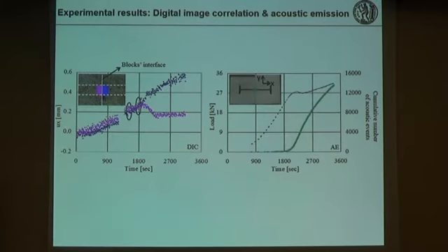And moving on to the results of the digital image correlation and the acoustic emission, on the left, in order to take advantage of the data of the DIC, what we did is we isolated two small rectangle areas at the front of the specimen, exactly next to the block's interface. And here you can see the displacement of the center of those two rectangles along the x-axis. So it is observed that up to a time of 1600 seconds, the displacement of both blocks is increasing.